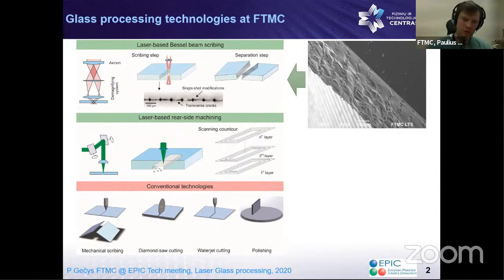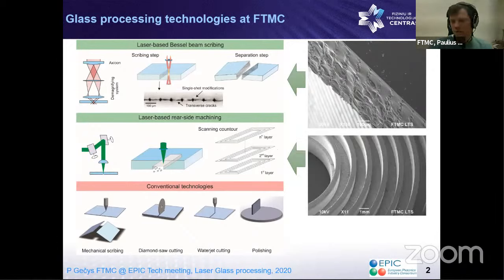The other technique I would like to talk about is, as I mentioned, rear side machining. This is a really flexible technique. You focus your laser beam through the glass sample to the bottom side, and by scanning your laser beam, you can form a cutting path. Scanning layer by layer, you can remove material from the backside, mainly in particle form. This is a really efficient process. We reached up to 120 millimeters per minute ablation rate, and what we tried is we can cut up to 19 millimeters thick glass.